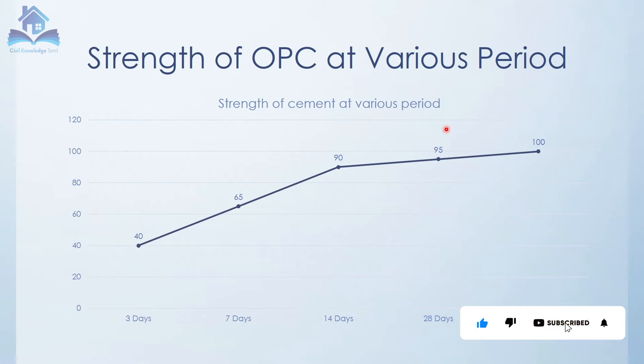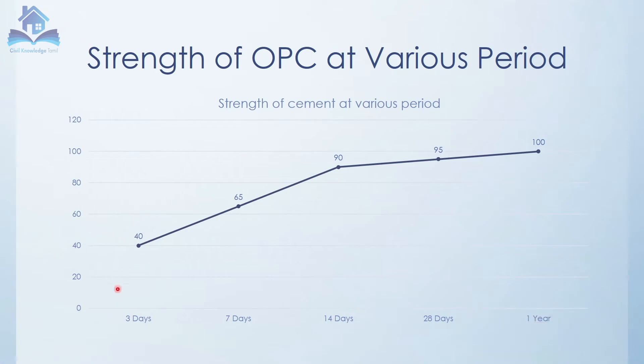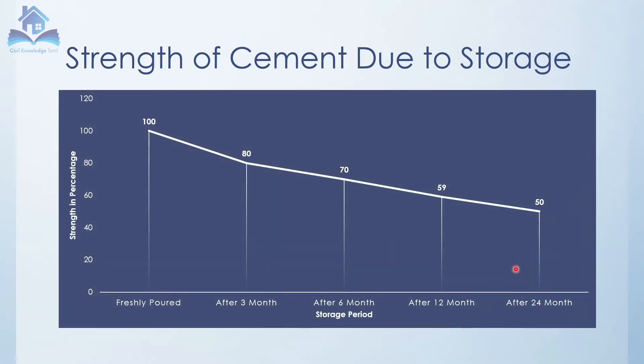In the next part, OPC cement is used for strong strength development. For example, in 3 days the strength is 40%, in 7 days the strength is 65%, in 14 days the strength is 90%, and in 28 days the strength is 95%. Over more than 1 year, 100% or more strength is achieved.